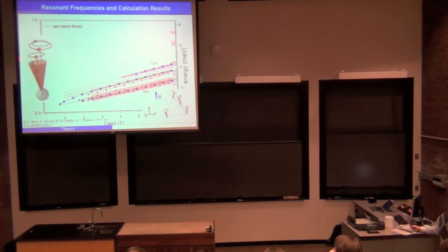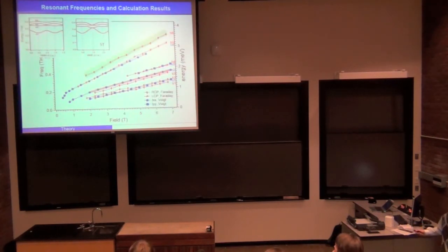So when the spins precess around this equilibrium position, if you look around the field direction, the motion instead of circular is elliptical. And an elliptical motion is a superposition of both a right-hand component and a left circular component. As a result, for this particular spin wave mode, the right circular polarized components all cancel out. They are all out of phase, leaving us with only a weak left circular component. So the spin wave calculation explains this feature nicely, and you can see the fitting agrees with the experiment quite nicely. And also, the spin wave calculation can generate, especially in the high field region, a dispersion relation, as I already showed you.